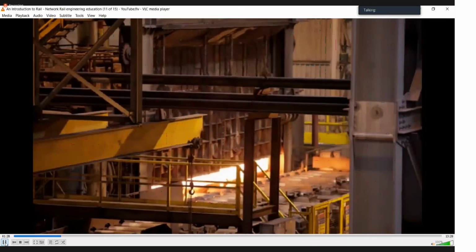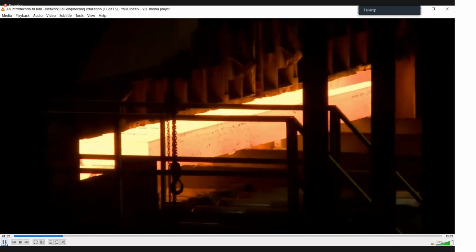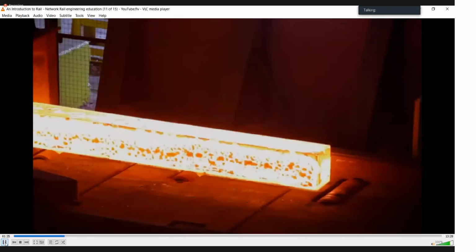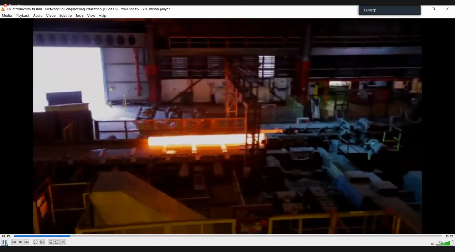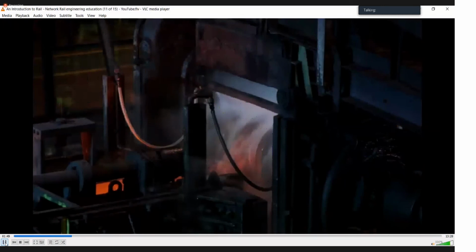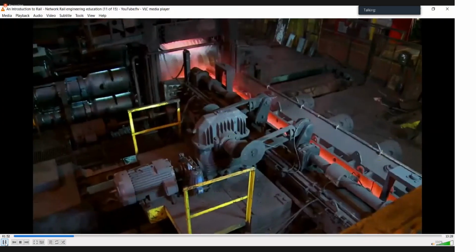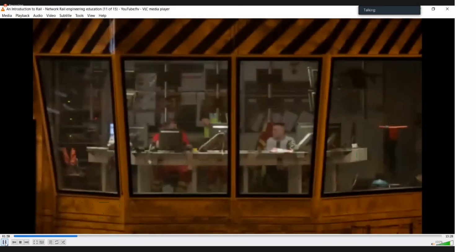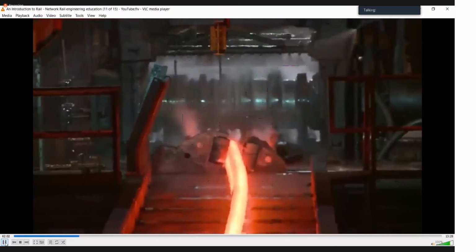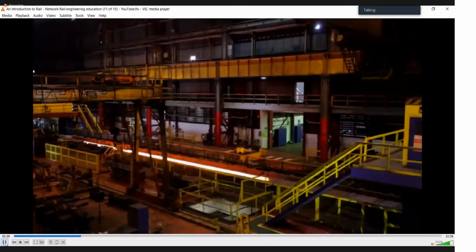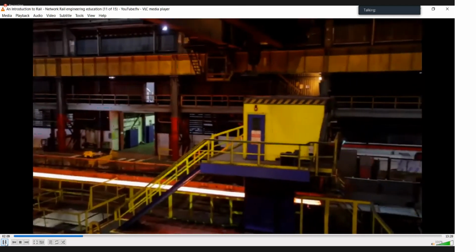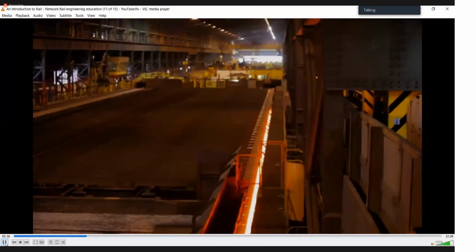The rail production process begins with 7.5 metre long blocks of steel called blooms, weighing 6.5 tonnes. These blooms are heated in a furnace to 1240 degrees centigrade to make the steel behave plastically and be capable of being shaped. The red-hot blooms are cleaned and descaled and then moved through the production line. Computer-controlled machinery squeezes, rolls and manipulates the blooms into a new form. In less than 10 minutes, the original bloom has a completely new cross-section profile and has been transformed from 7.5 metres to just over 108 metres in length.